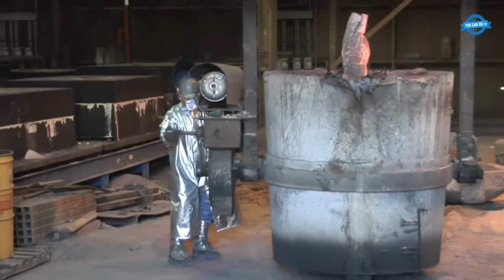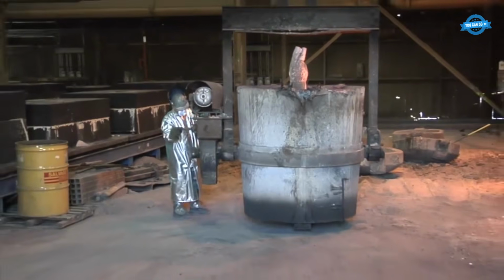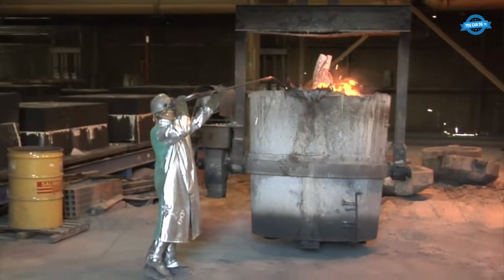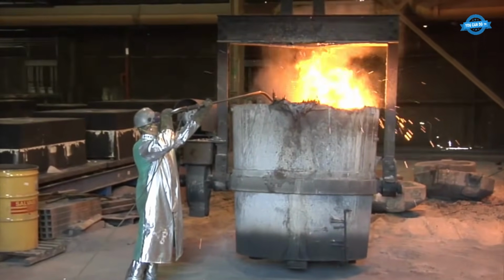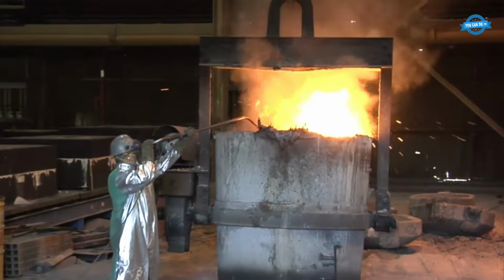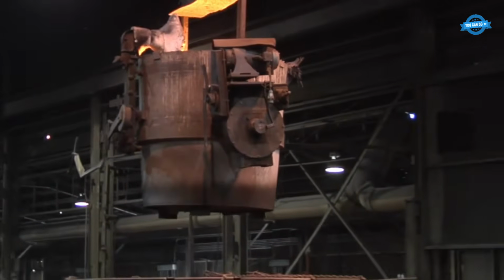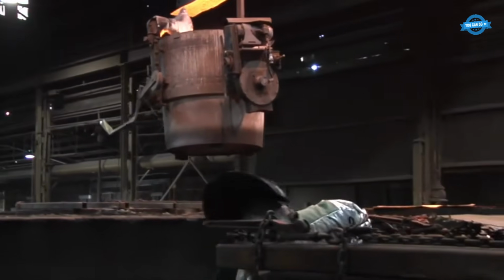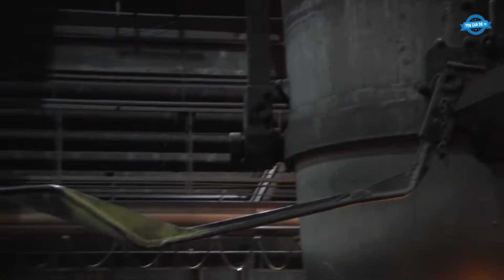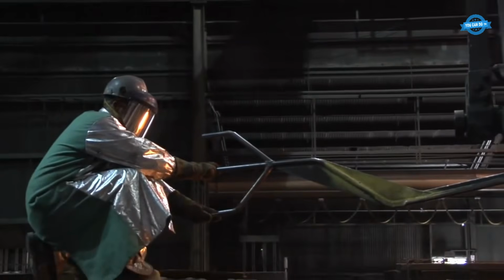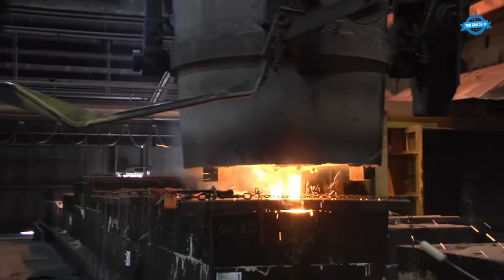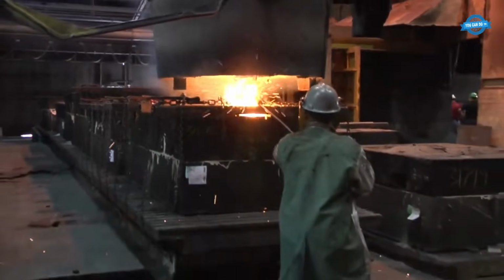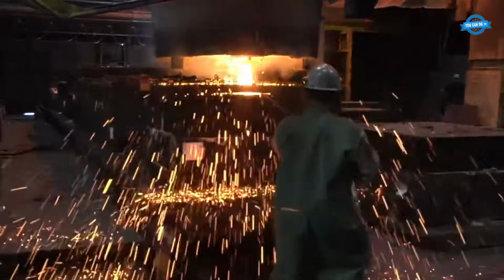This no-bake center averages 4 molds per hour and 40 to 48 daily. Sand mixed with furan binder hardens in about 20 minutes, then rollover equipment strips it from the pattern. Cores, refractory coating, oven drying, inspection, glue, and locators follow in tight order. The challenge is sequencing. The right mold must reach the right station when the heat taps on the pouring floor.